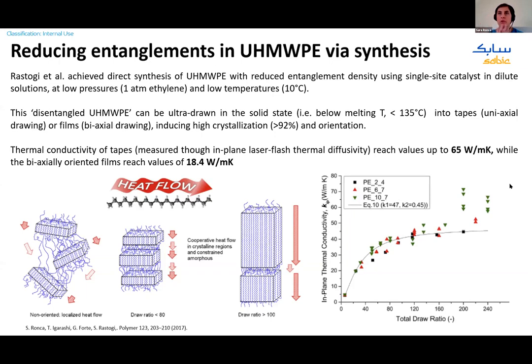You can compression mold this material into a coherent plate below the melting temperature, and you can stretch this material uniaxially into tape or even biaxially into films, inducing very high crystallization and very high orientation.